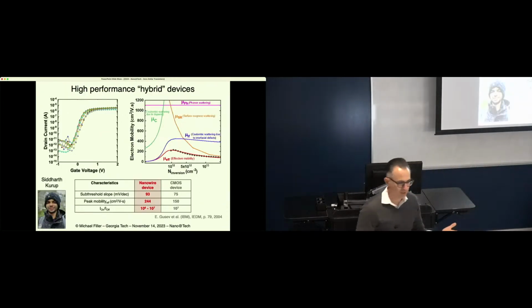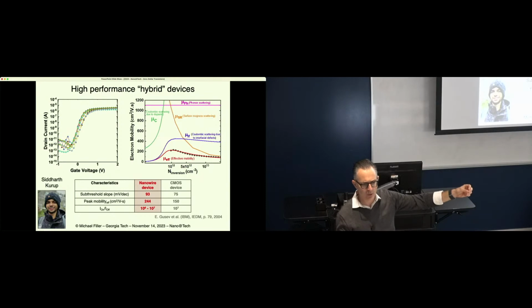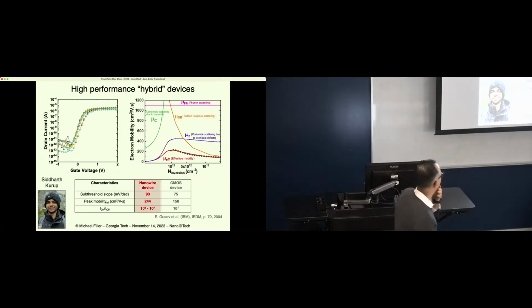nanometers. One of the first questions is, okay, now you're growing crystals with a seed particle. Is the material you're making going to yield high-quality transistors? And so Siddharth has done a bunch of work taking bottom-up grown wires and applying top-down fabrication techniques to build MOSFETs out of them, just to prove out that the nanowire materials are good for what we're trying to do. And so again, you see IV curves. And here he's characterized the types of scattering processes that might be limiting us. But the bottom line is we're getting hundreds for mobilities and decent on-off ratios when we do this. So we're not really worried that the crystal growth is going to be limiting in any way, shape, or form.